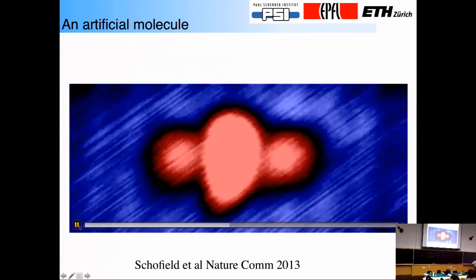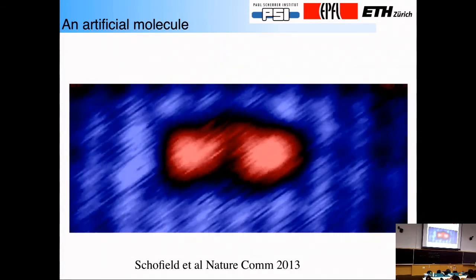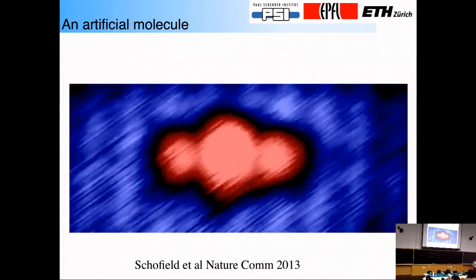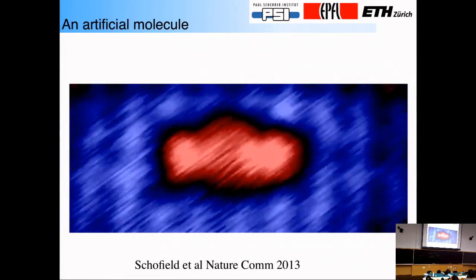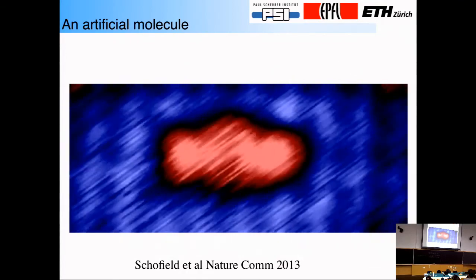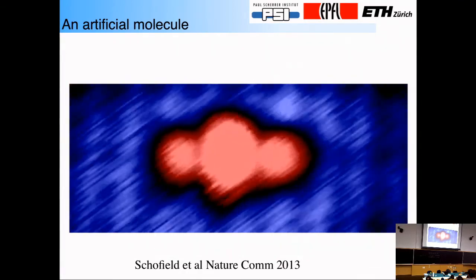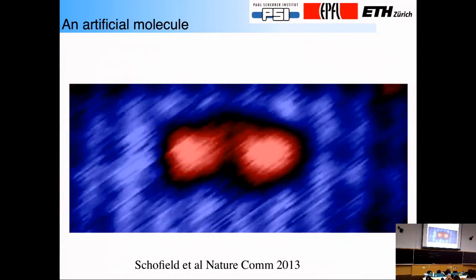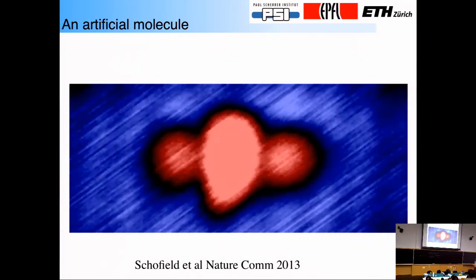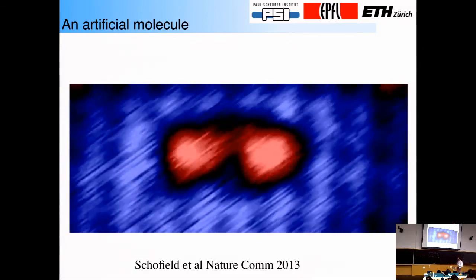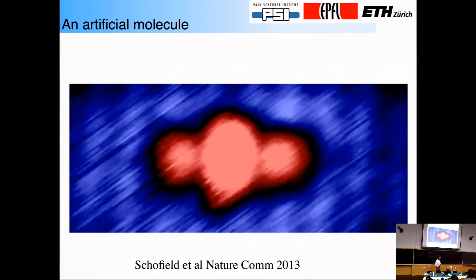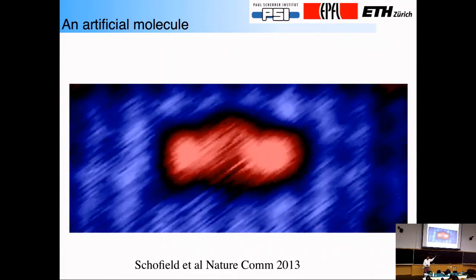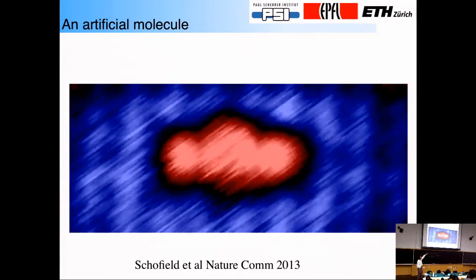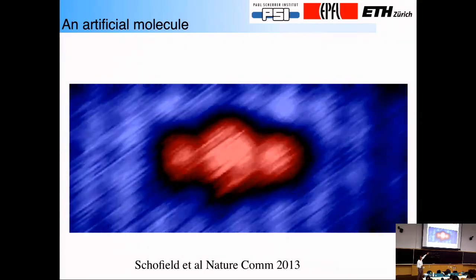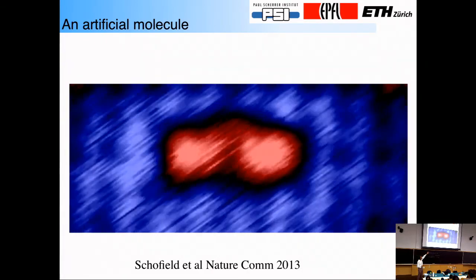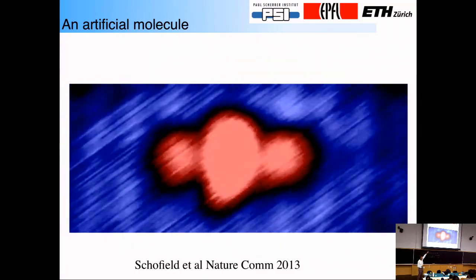What I'm doing here is I'm now changing, in this case, the tip-sample distance. And what's very interesting is that as I change that tip-sample distance, of course, I'm changing the electric field at the sample. And as I change that electric field, I'm actually finding that the image changes. So what I'm doing here somehow, with my STM tip, is changing the nature of the orbital. I'm actually switching the orbitals that live in this dimer object. Sometimes you see two things at this side, and at other times you see three things with a very bright object in the middle.